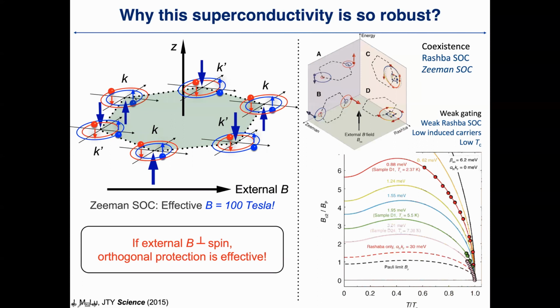So if we have a pairing across the K and K prime through the gamma point, then this blue electron is going to be paired with this red electron, and this blue electron can be paired with this red electron. So then we have a pairing that is across the Brillouin zone, and at each K and K prime point, the pairing is actually protected by a very, very strong Zeeman field there. So take the Zeeman SOC at K and K prime point. This is more or less equivalent to a B field of 100 Tesla. So we have a 100 Tesla protection over here.